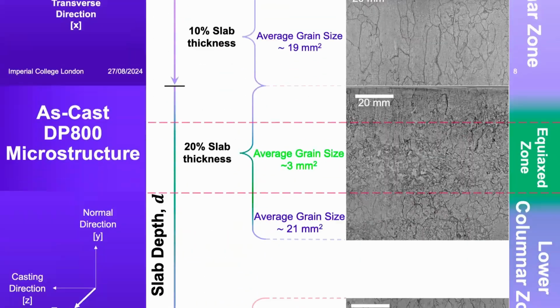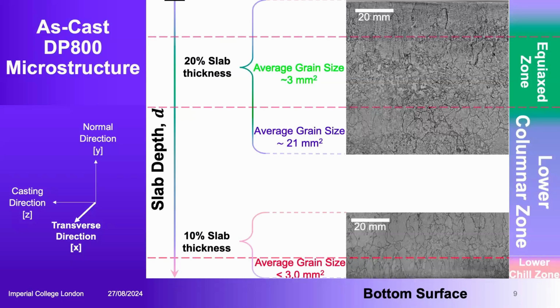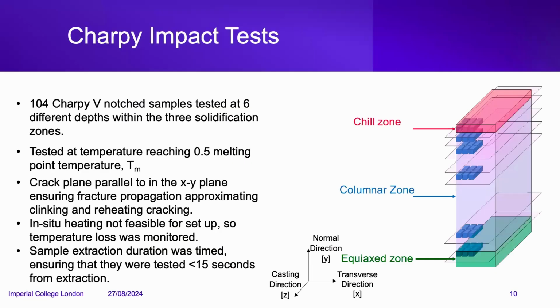So as we move down the slab, the columnar zone makes way to the equiaxed zone, relatively in the center of the slab, with an average grain size of 3 millimeters squared. And then this again moves down to another columnar region and the chill zone in the bottom. So having determined the solidification zones, I was able to extract samples for testing.